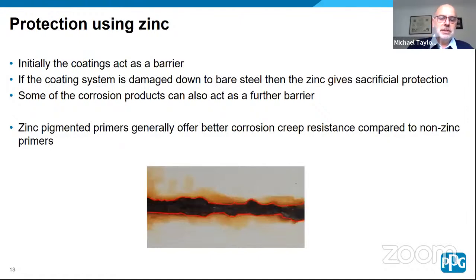Protection using zinc, Martin went through this beforehand, but initially the coatings act as a barrier, and then if the coating is damaged down to bare steel, then the zinc will give some sacrificial protection. And some of the corrosion products can also act as a further barrier. Zinc pigmented primers generally offer better corrosion creep resistance than non-zinc primers. So the creep resistance is, as demonstrated in the photograph, where you have a damage to the coating film down to the steel. There's a tendency for the corrosion to spread from that damage underneath the coating film. Zinc pigmented primers are far more efficient at preventing that spread, so the damage is usually limited until you have a chance to repair it.